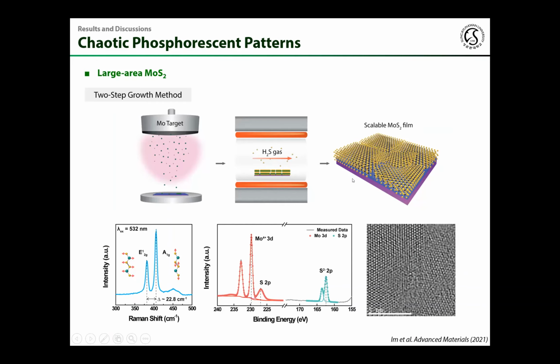As synthesized, the film consists of bi- or tri-layer amorphous structures with nanometer-scale MoS2 grains. These films are characterized by Raman and XPS analysis, revealing great quality relevant to MoS2. And the TEM image of this film shows it contains randomly oriented small grains.